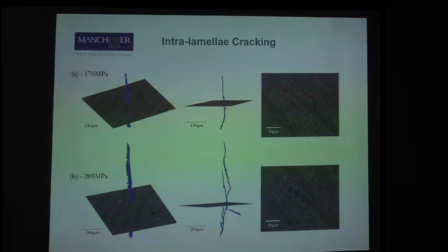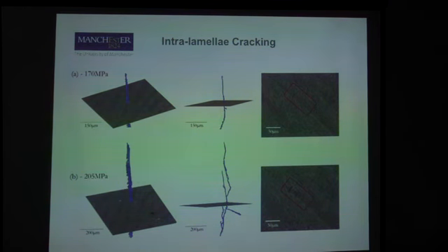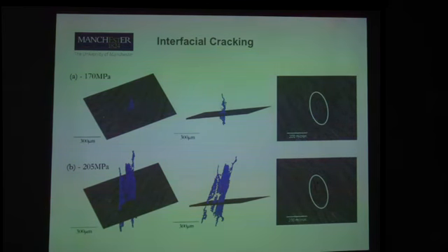That's the order in which the process is occurring. So these cracks are forming and then at later stages coalescing. And the reason I've only shown these two lower loads is that at higher loads, everything gets a lot more complicated because there is much more interconnectivity then, and it's difficult to distinguish between cause and effect.